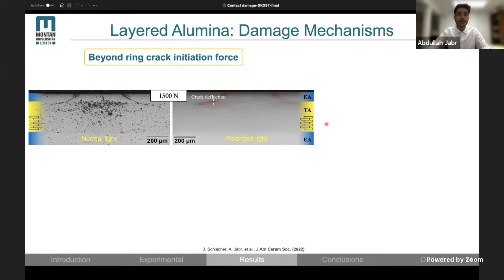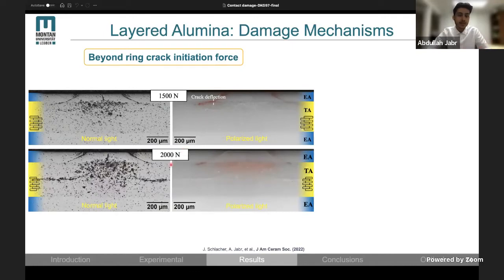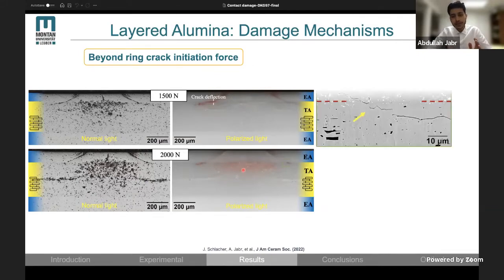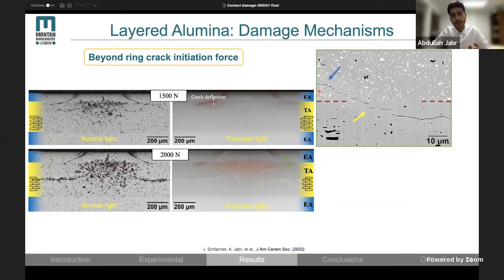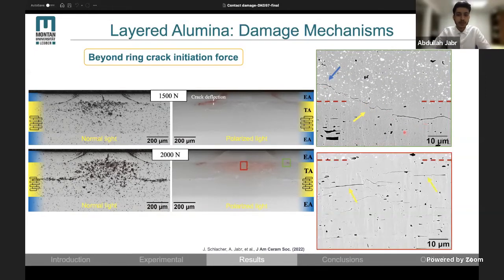Now let's see what happens beyond the ring-crack initiation force, meaning at even higher forces. Here is a cross-sectional view of a sample loaded at 1500 Newton. In the normal light image, you can see the subsurface damage in the internal textured layer. In the polarized light image, we can see the deflection of the cone crack at the internal textured layer. If we increase the load to even higher force, we can see that the subsurface damage intensifies. But what's interesting is that the cone crack remains limited in depth, meaning that further damage was then only absorbed by the internal textured layer. Looking at the interface using the ion-slicing technique, we can see the deflection of the cone crack along the textured grains, and again the subsurface shear faulting in the form of micro-cracking along the grain boundaries.